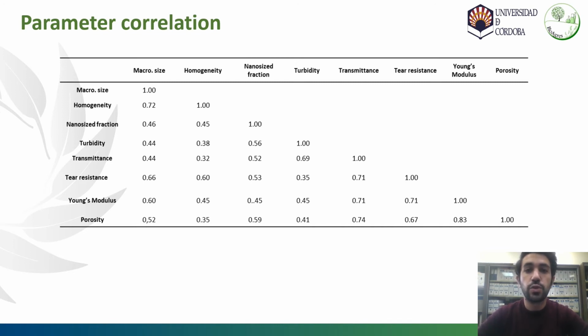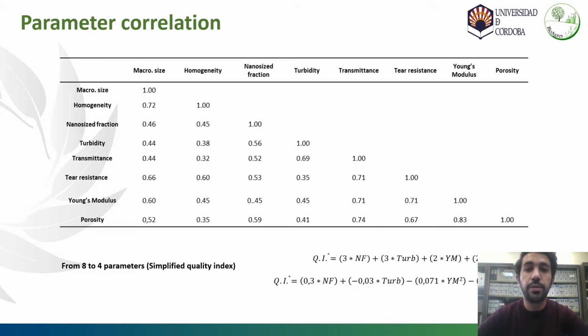After this analysis, it was concluded that there are 4 parameters that are really independent of each other, thus setting the parameters to be analyzed for the calculation of this index: the nanofibrillation fraction, the turbidity of the suspension, the Young modulus, and the macrometric size, obtaining a new quality index for the calculation of this simplified quality index.